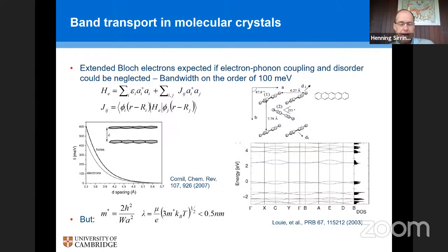But if you are an inorganic semiconductor physicist, you might look at these molecules and they might not look too dissimilar to you than a covalently bonded semiconductor like silicon. So here you've got a picture of the crystal structure of one of these conjugated molecules, this 5-fused benzene ring here, this molecule we call pentacene. And you can form single crystals of pentacene. And typically the molecules in the single crystalline structure arrange in a layered fashion, where within the conjugated layers you have this characteristic herringbone stacking.